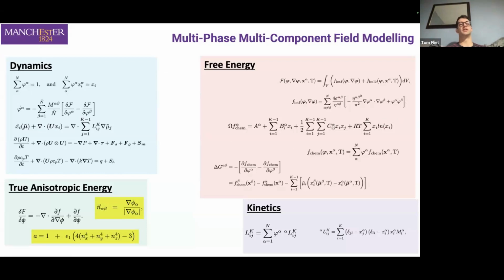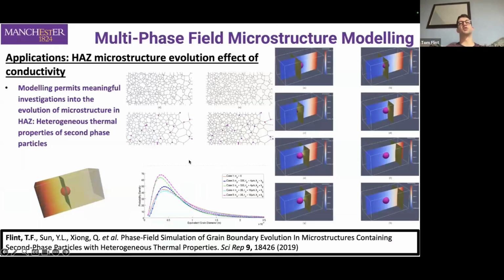This is really good for things like solidification. We're working on implementing another form of this for interstitial chemical components. What we've done that's really novel is fully capture the anisotropy of the system. That's important because in solidification, with the dendrites that form in metals, you have to capture the interfacial energy anisotropy to properly predict those dendritic structures. No other phase field formulation has done that. We're the first to fully capture that anisotropy, and that allows us to predict these really nice microstructural evolution